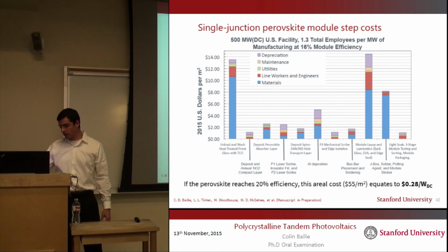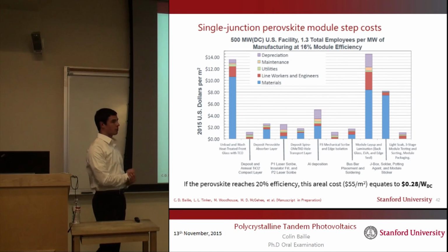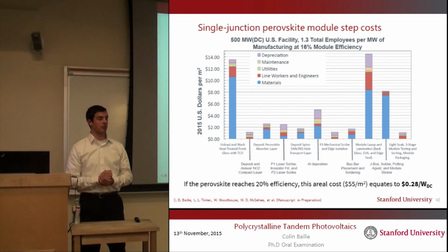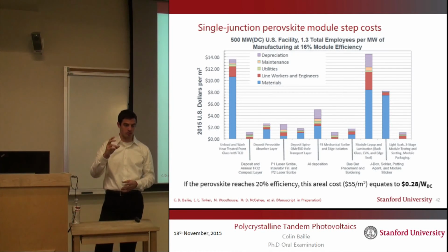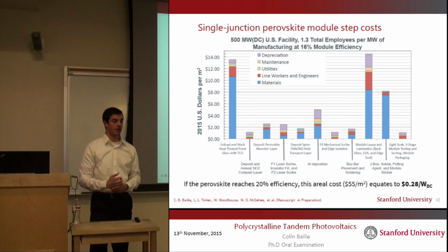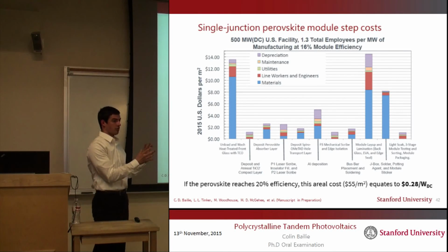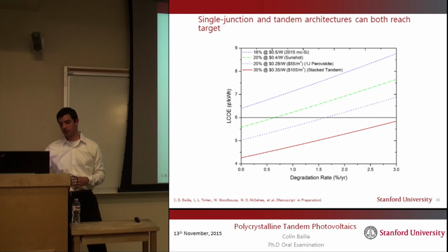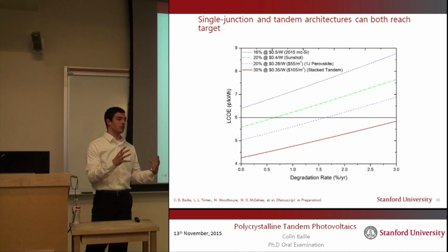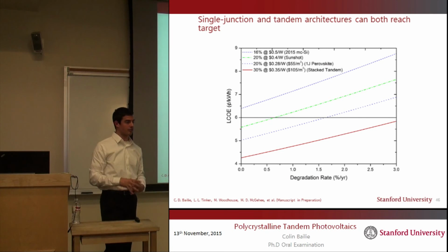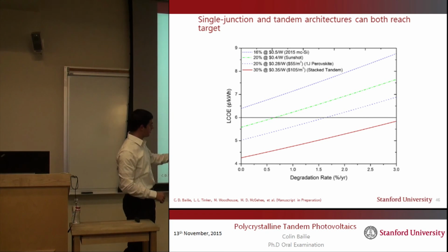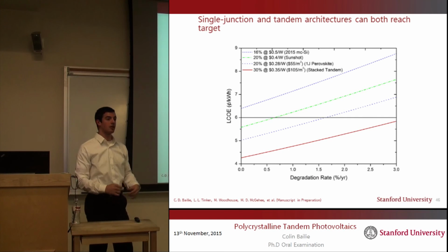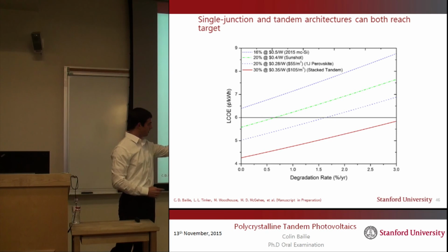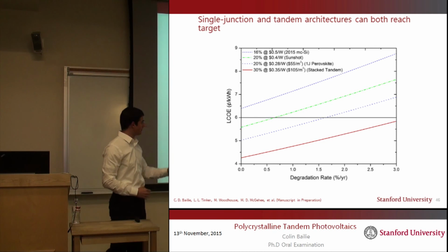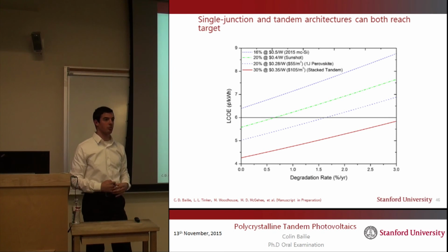So in this style of the cost, this is in dollars per watt. And when you say dollars per watt, you're saying dollars per immediate watt. So how many watts your module produces at time 0. So this doesn't take into degradation at all. When you're calculating LCOE, it does take into account the entire lifetime of the system. And so down here at the bottom, you're seeing the LCOE as a function of degradation rate. So if your perovskite is degrading faster, then you're further on to the right of this chart, and your system is more expensive.